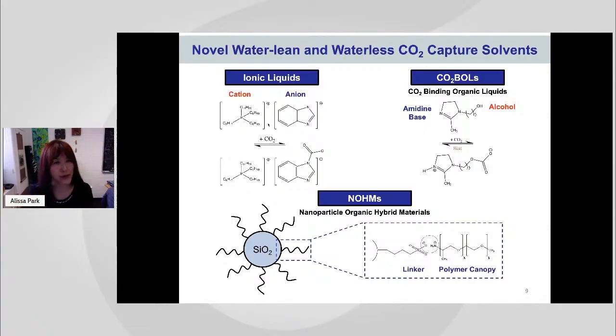But we did not really particularly want to make ionic liquid. It just takes a lot of organic synthesis. But that was about the time my colleague Lynden Archer at Cornell contacted me and said, Alissa, we made a really unique material called NOHMs, which is nanoparticle organic hybrid materials. He wasn't really thinking about CO2 capture, but what he was saying was that by tethering liquid polymer onto an inorganic nanoparticle like silicon dioxide, the final product is still a liquid-like material, but with enhanced thermal stability.